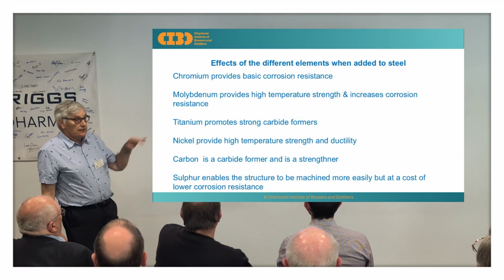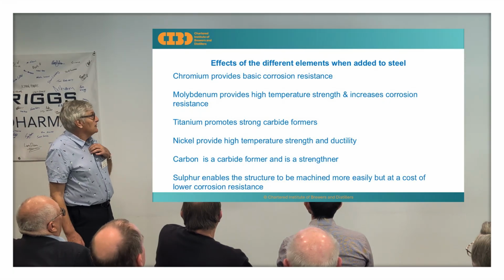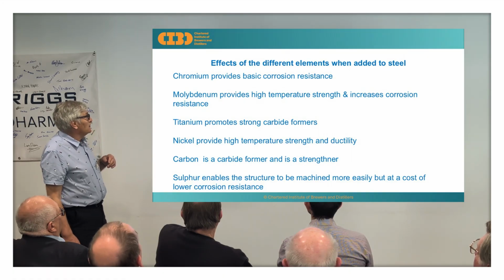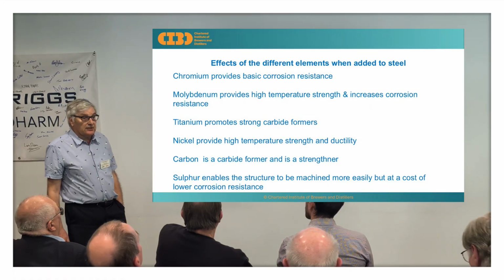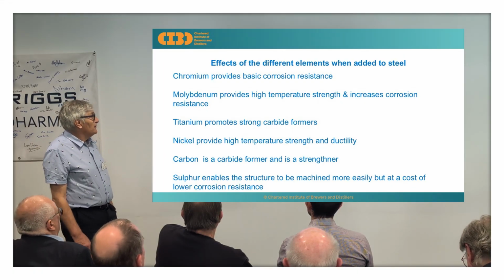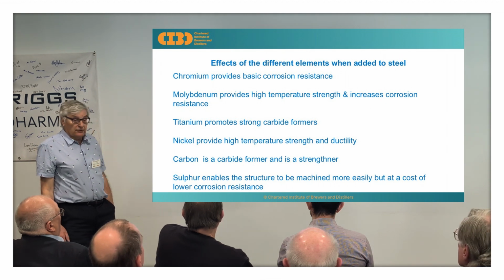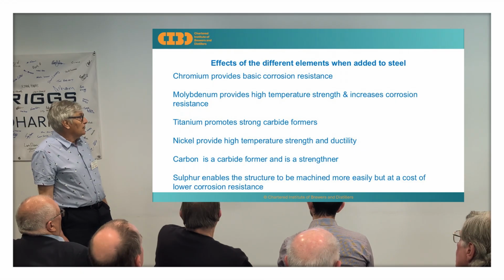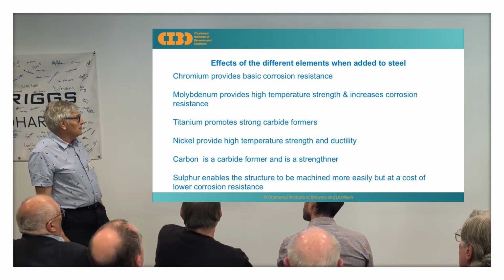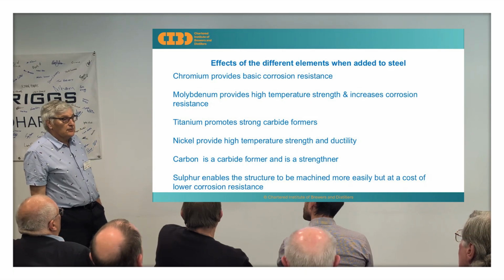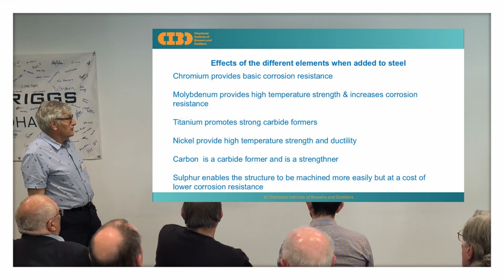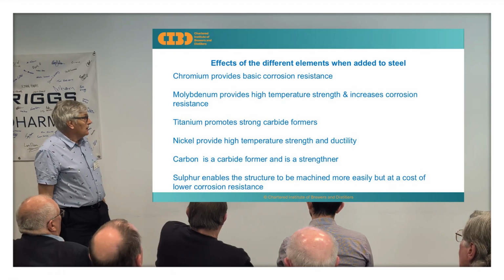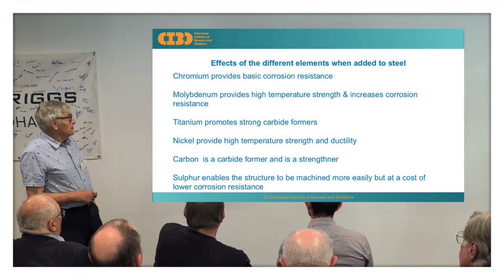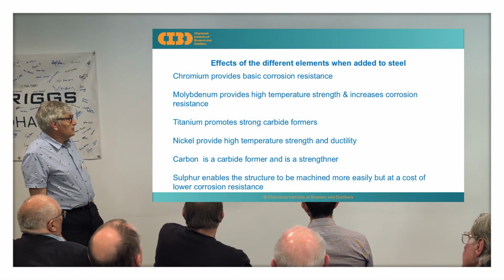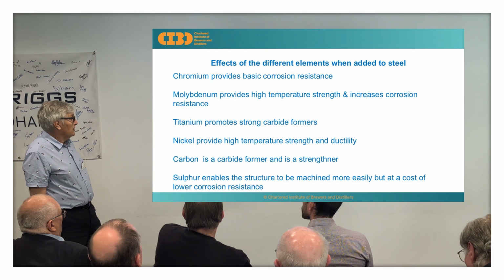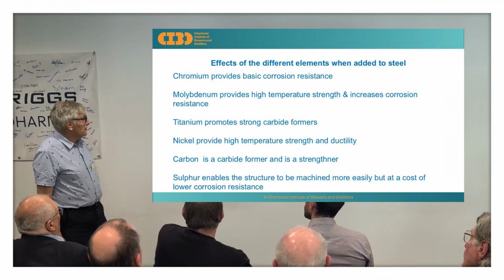Right. You saw in that table earlier there are the different elements, and what do these elements bring to the party? Well, the chromium provides the basic corrosion resistance. The molybdenum provides high temperature strength and increases corrosion resistance. Titanium promotes strong carbide formers. If I'm right, you saw that in the 321, and I believe that is quite good for machining properties. Nickel provides high temperature strength and ductility. Carbon is the carbide former and is a strengthener. The sulfur that we saw in that 303 does enable the structure to be machined more easily, but at the cost of lower corrosion resistance, and it doesn't take to welding to a higher standard.